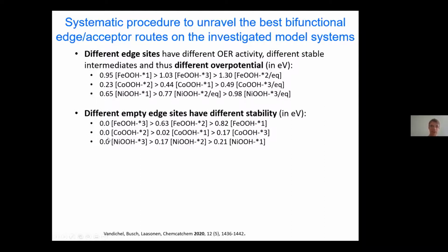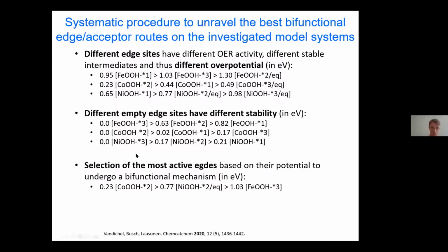So if we have this star 3 as most abundant active site, it doesn't mean, because it's most abundant and most stable, that the reaction takes place on these sites. So this is just to say that everything is quite complex.